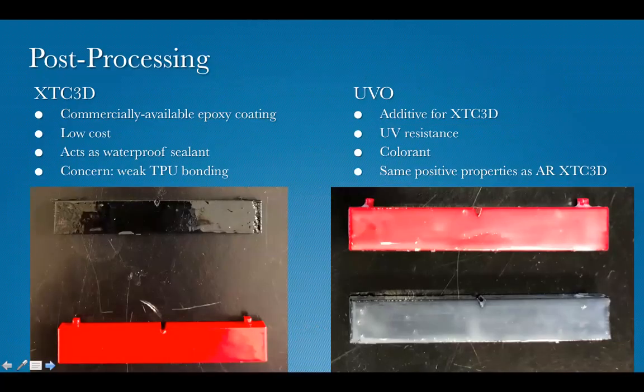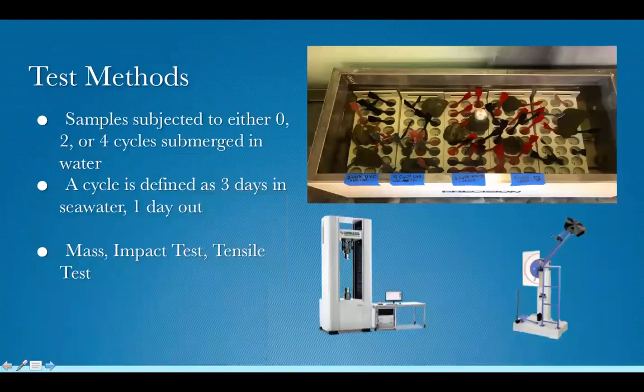Both the TPU-92A and ASA samples were coated in XTC3D and XTC3D with UVO in an attempt to increase the impact toughness and water resistance of each sample. XTC3D is a commercially available epoxy coating, which can be combined with UVO colorants to increase the UV resistance of a material. The sample set was divided into three groups, one for each of the aforementioned coatings and one left uncoated.